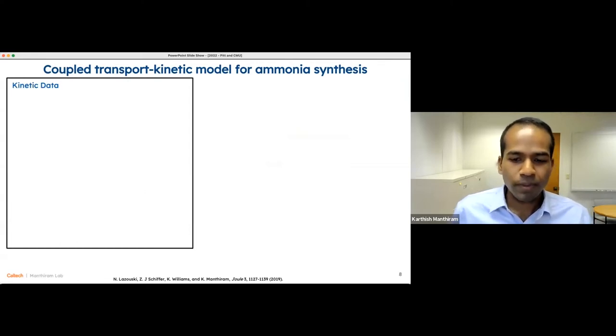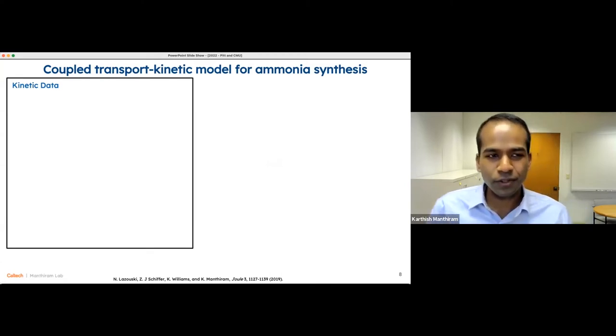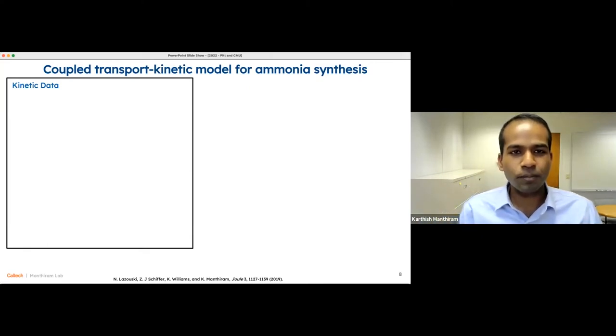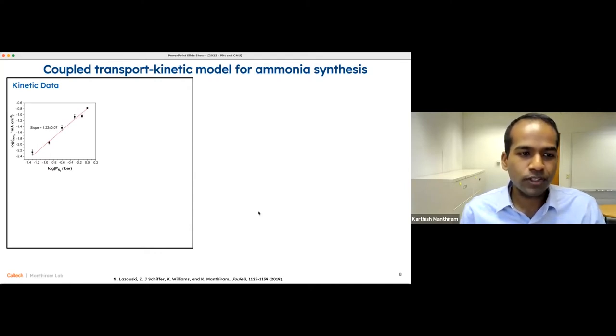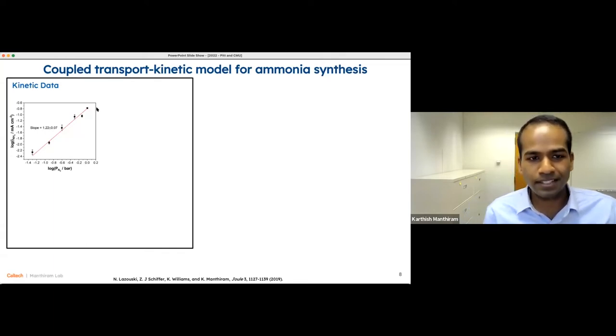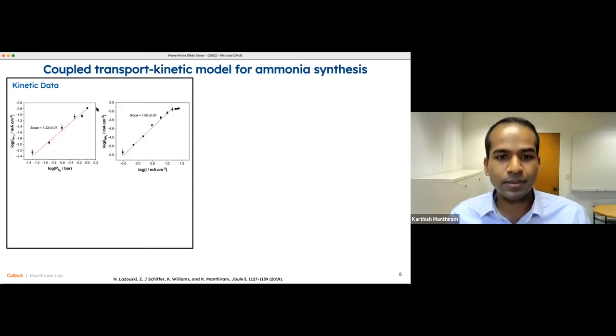So with a reproducible method and one which is confirmed with isotope labeling, we set out to understand the kinetics of this process. And I'll show here just a few samples of that kinetic data to help give some idea of how we conduct these kinetic analyses. So first, for instance, measuring the order dependence for ammonia synthesis for the partial current as a function of the partial pressure of nitrogen. And you'll see here an approximate first order dependence, which is unsurprising given how we expect nitrogen to be a reactant in this chemistry.